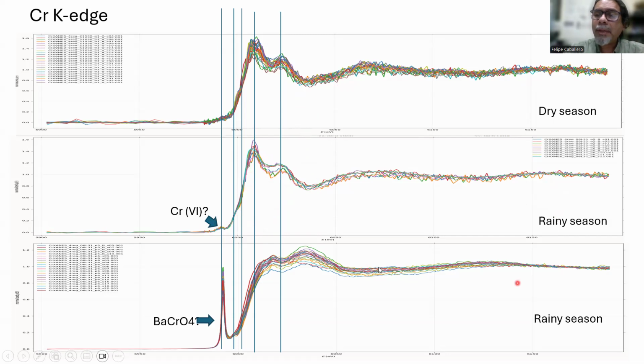We have a very nice, very interesting finding: the spectra obtained through the rainy season samples show this particular shape that is associated with barium chromate. Barium chromate is a substance that is used in anti-corrosive coatings, and we can remember that anti-corrosive coatings are used in ships, in oil drilling platforms, and in conduction pipes for petrochemical derivatives. So it's possible that some of these particles that were measured and identified as chromate come from the erosion, the leaching of these particles from coated structures.